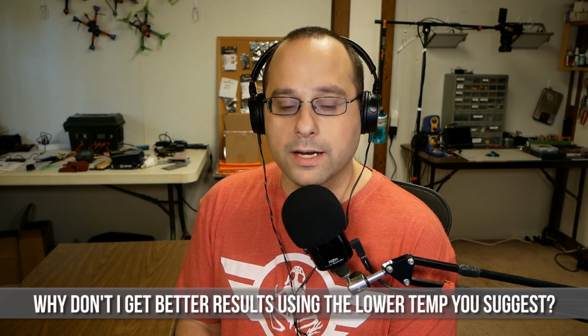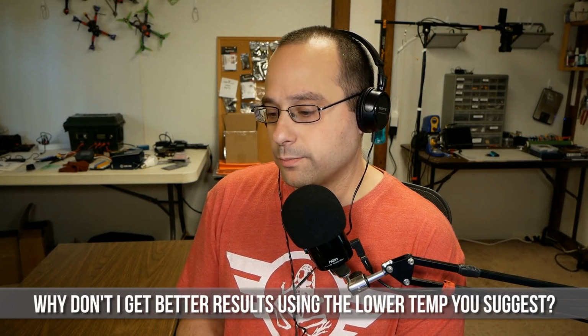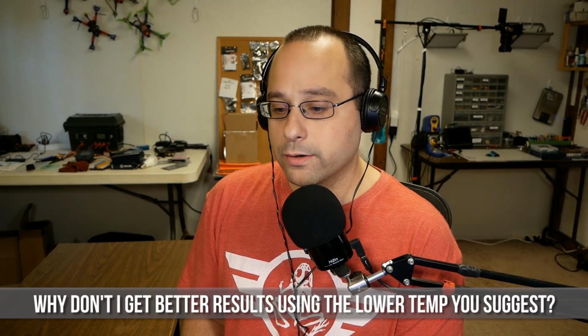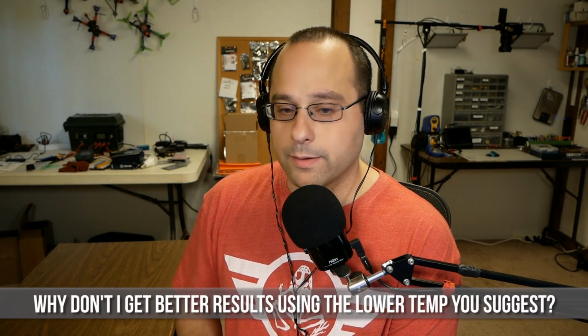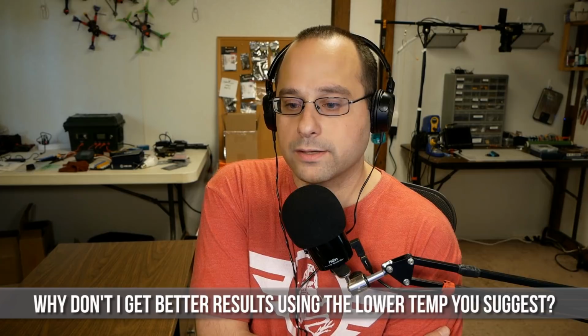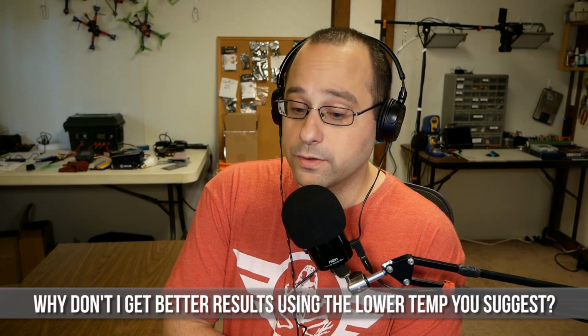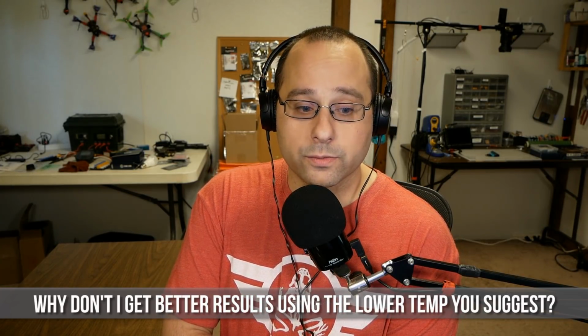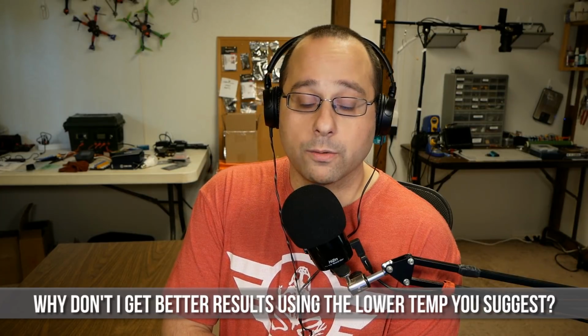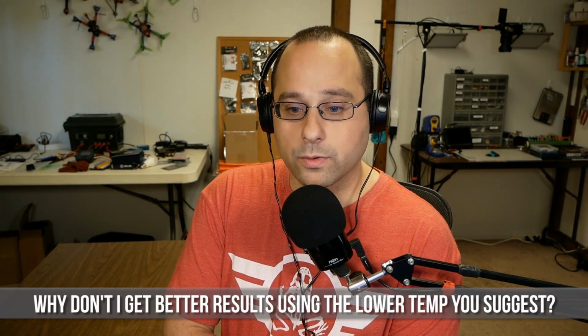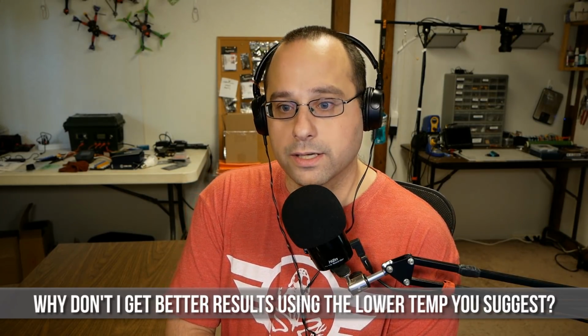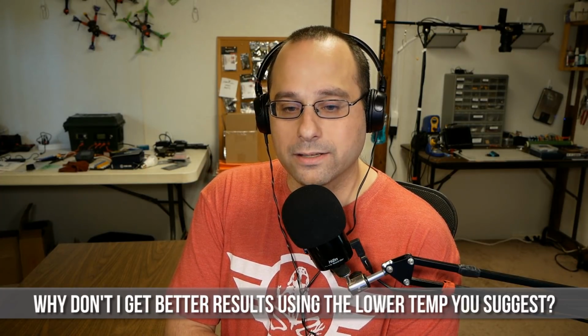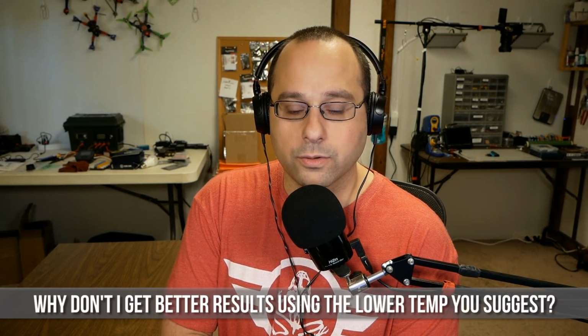I think that's probably true for most people in this particular branch of the hobby. Not a lot of us are soldering components to boards so much as we are soldering wires to boards. And maybe then the additional thermal mass of the wire is going to mean, especially if you're doing larger wires like ESC wires, which might be 18 or 20 gauge, or main battery leads where we're up to something like 12 or 14 gauge, you're going to need a higher temperature just to get the heat into the wire quickly enough to make the joint work.